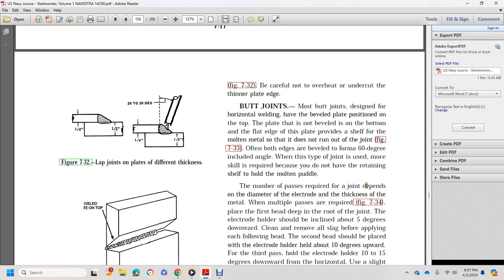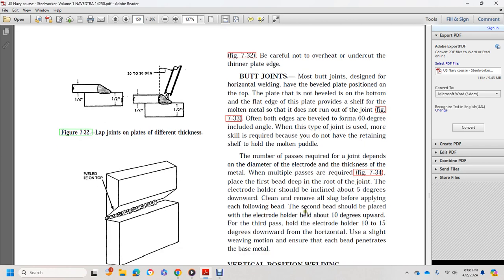The number of passes required for the joint depends on the diameter of the electrode and the thickness of the metal. When multiple passes are required, as in Figure 734, place the first bead deep into the root of the joint. The electrode holder should be inclined about 5 degrees downward. Clean and remove all the slag before applying each of the following beads. The second bead should be placed with the electrode holder held at 10 degrees upward. For the third pass, hold the electrode holder 10 to 15 degrees downward for the horizontal. Use a slight weaving motion and ensure that each bead penetrates the base metal.